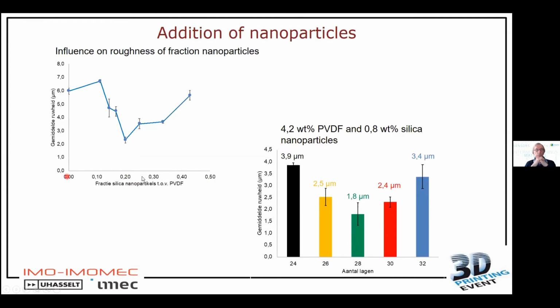Here you see the amount of nanoparticles in the PVDF acetone solution, and you see the roughness. If we depict it here, you see, for example, that if we put 28 layers having 4.2 weight % of PVDF and 0.8 weight % of silica nanoparticles, we achieve a roughness of around 1.8 micrometers, which is lower than the 2.2 micrometers that we would like to achieve with 28 to 30 layers. And doing a cross section, it seems that we have the results that we would like to achieve. So this is the industrial standard that we aim for.